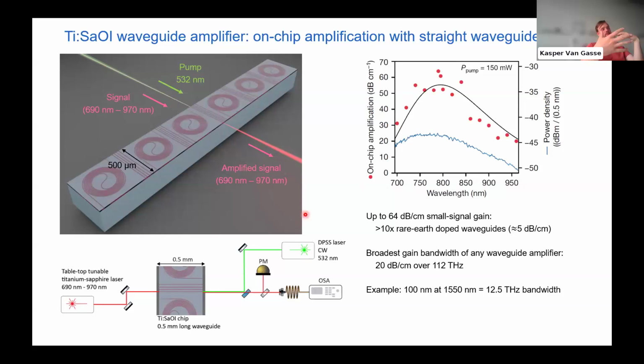Because now we can compare one-to-one with, for example, the rare earth doped silicon nitride waveguide amplifiers. And then we see that we actually achieve almost 10x more amplification in our waveguides than in the rare earth doped ones.